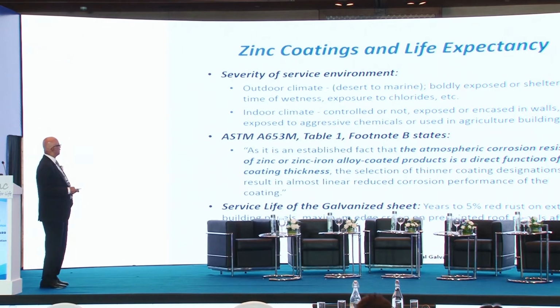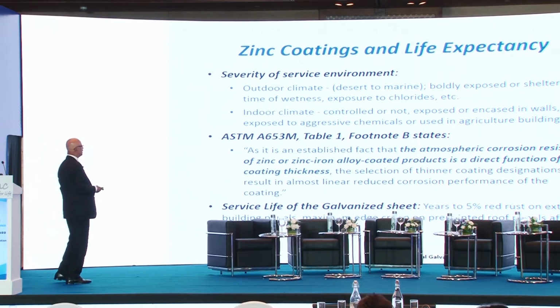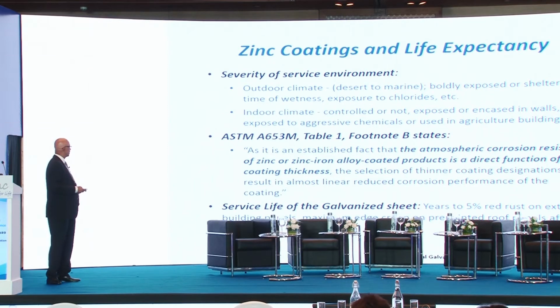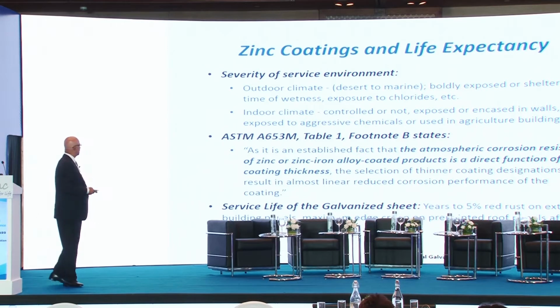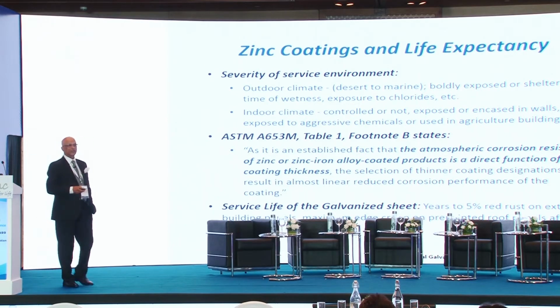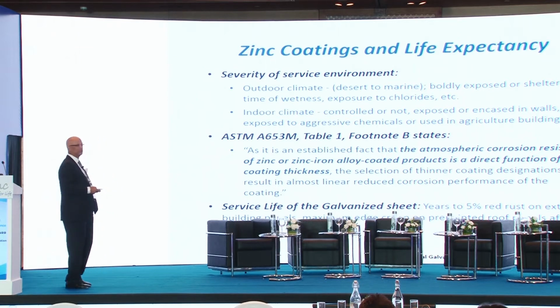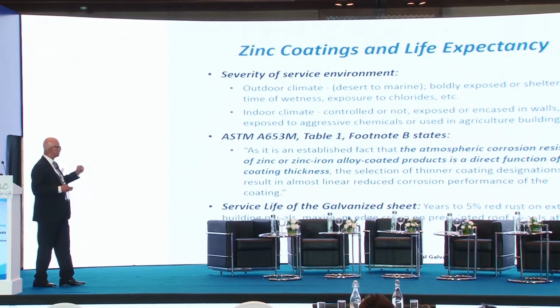ASTM A653, which is sort of the IS 277 equivalent in North America, says very clearly that the atmospheric corrosion resistance of zinc or zinc iron alloy coated is a direct function of its coating thickness. And the selection of thinner coating designs, lighter coating weights in other words, will result in an almost linear reduced corrosion performance of the coating. So while everybody tries to save money and reduce coatings, we're actually shooting ourselves in the foot because we are intentionally reducing the life of the building.